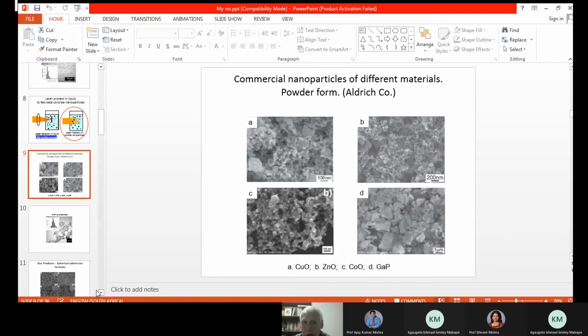So we tried using the commercial nanoparticles, prepared the colloid with these nanoparticles, and tried to ablate this colloid by a non-focused laser beam. Our result is shown in this picture. We were surprised. We produced very, very nice spherical particles with a rather small particle size distribution. The particle size could be, for example, 320 plus minus 50. So this is not a bad result. Okay, let's move next.